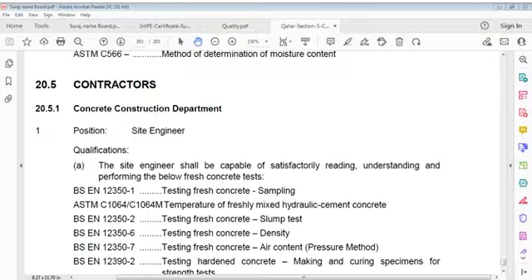For concrete of conventional proportions, a reduction of concrete temperature of 1 degree Fahrenheit requires reducing either cement temperature about 8 degrees Fahrenheit, water temperature about 4 degrees Fahrenheit, or aggregate temperature about 2 degrees Fahrenheit. So cement temperature 8 degrees, water temperature 4, and aggregate temperature 2; it is in that proportion.